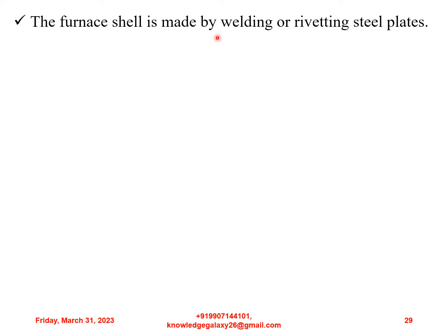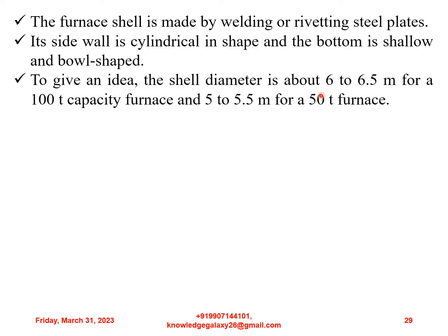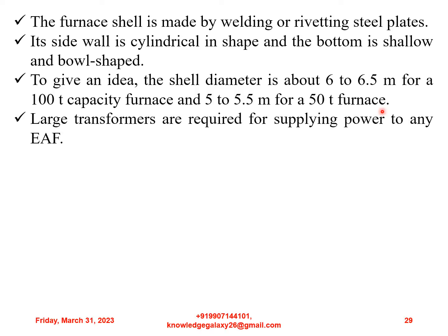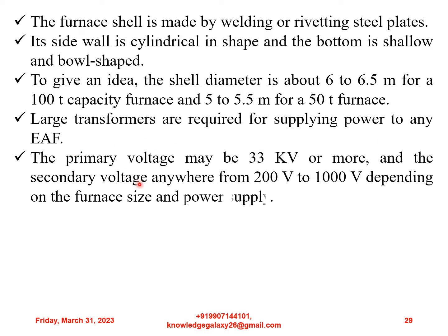The furnace shell is made by welding or riveting steel plates. Its side walls are cylindrical in shape and the bottom is shallow and bowl shaped. To give you an idea, the shell diameter is about 6 to 6.5 meter for a 100-ton capacity furnace and 5 to 5.5 meter for a 50-ton furnace. So this is a typical idea, need not be exactly the same for each and every furnace. It varies. Large transformers are equipped for supplying power to any electric arc furnace. The primary voltage may be 33 kilovolt or more, and the secondary voltage anywhere from 200 volts to 1000 volts depending on the furnace size and power supply.